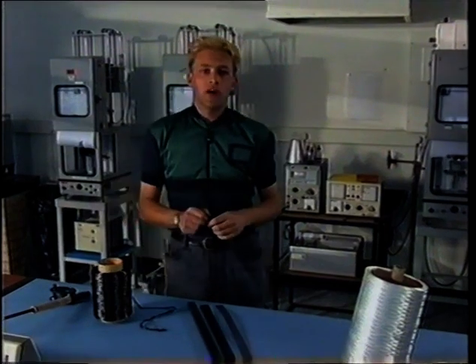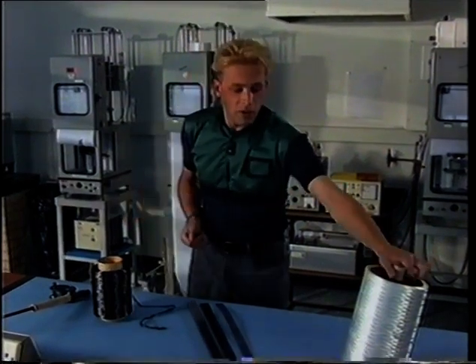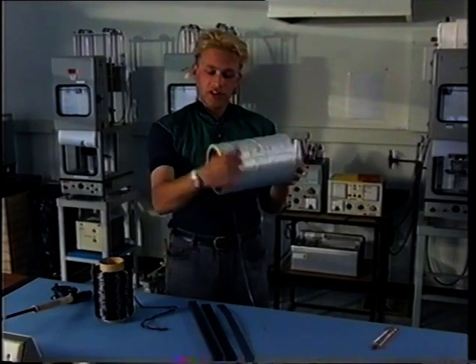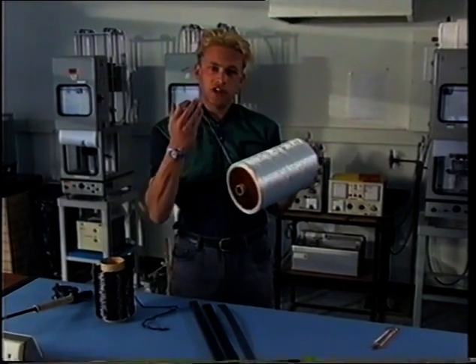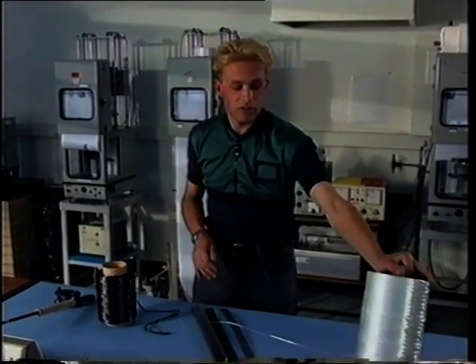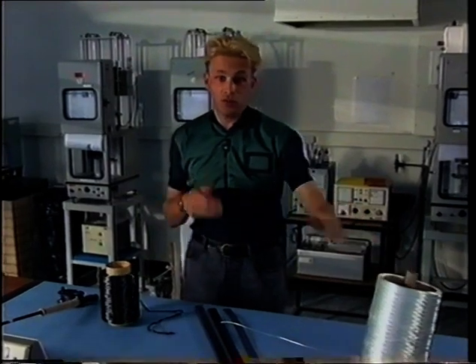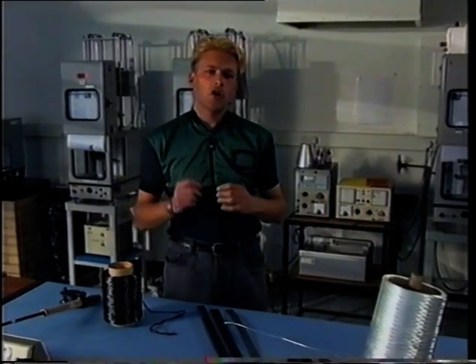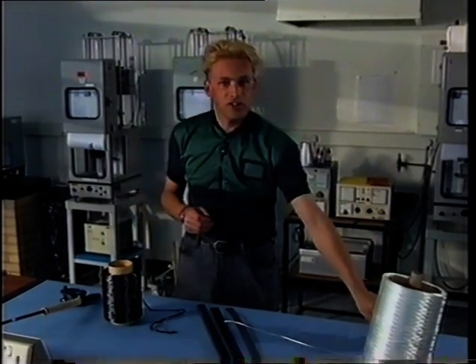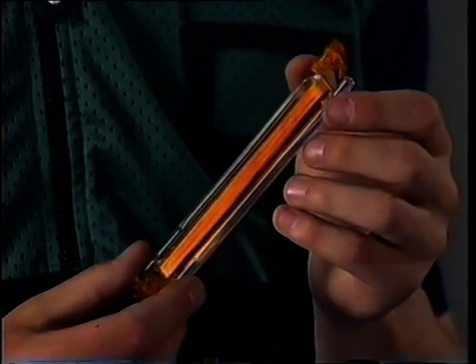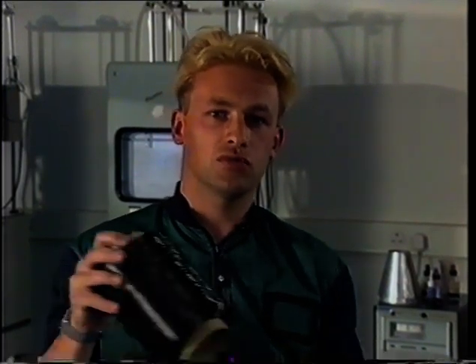Now, carbon fibre is made relatively easily from an acrylic polymer fibre such as this, and through a 2-stage reaction, the first of which carried out at about 200 Celsius, the sort of thing you could do in your oven at home, but in an oxidizing atmosphere, produces this material. The second, or carbonisation reaction, requires a much higher temperature, in fact temperatures of over 1000 Celsius, and no oxygen at all. And that gives us the final product, true carbon fibre.